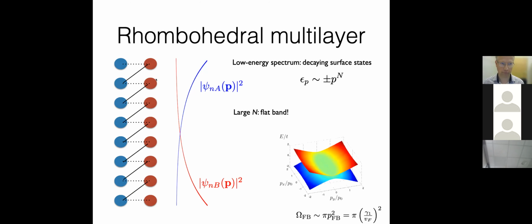that depends on the size of the momentum with respect to the coupling gamma 1. And so you have these surface states, and they have a dispersion which goes roughly like p to the nth power, where n is the number of layers. So if you now make n very large, you have a flat band. The size of the flat band in this case is given by the size of the coupling gamma 1, and the scale comes from the Fermi velocity in the single layer.